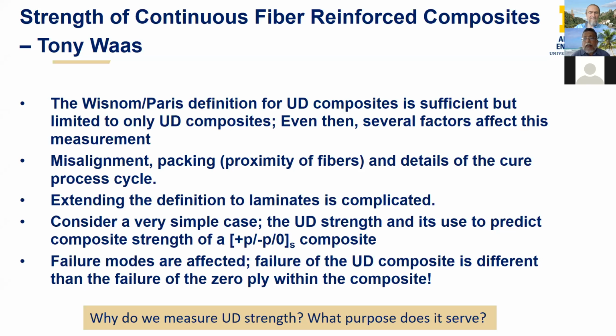Small misalignments tend to load the matrix in shear. And what happens is, if you keep loading it, if the interfacial strength or the interfacial toughness is exceeded, you can get splits. And these splits are energetically favorable because it wants to release the residual stresses in the matrix. That then immediately shifts the load to the fibers, and the fibers can break suddenly because of overload. So the scenario I'm outlining here shows that even for a UD composite, which I think is a structure, even for that, the failure strength, or the Wisnom Paris definition, can be problematic.